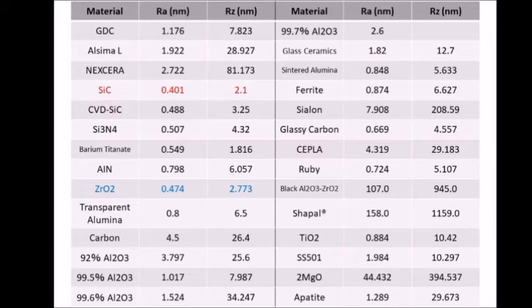Let's move on to the material ceramics. We have polished 28 types of ceramics, such as typical alumina, ruby, and other ceramics. The best roughness here is SiC, Ra 0.4 nanometers and Rz 2 nanometers. This SiC stands for silicon carbide.